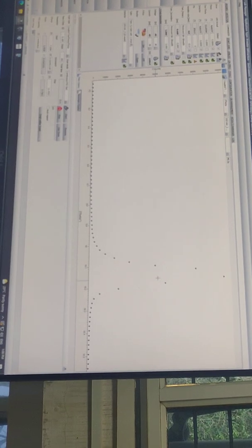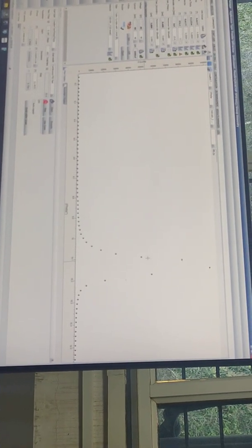So now I am doing only that particular region. Okay, good. I'm having better. So now again I'm converting into data points. Now I have more than 1 lakh counts, but still, if I see above 50,000, I have only 2 or 3 data points. So still, it is not meeting my criteria.